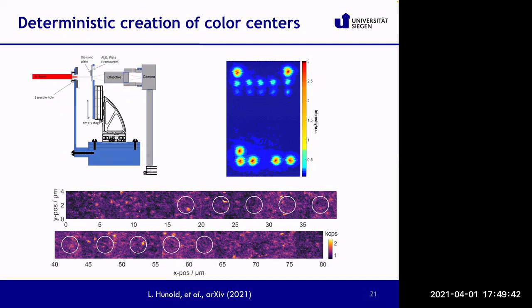So you see a sketch of the setup, in which you get the ion beam, then you have the pinhole, and then you hit the diamond sample on a translation stage, and then you create these patterns that you see on the top right. By changing the fluence, you get brighter or less bright spots.